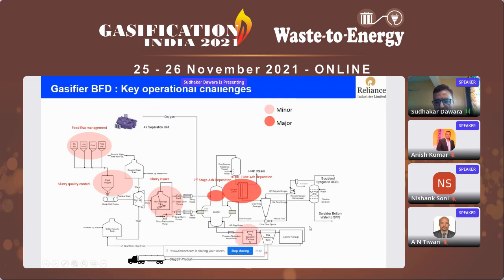Now, of course, we had many issues in the char filter. We have overcome that. We redesigned the metallurgy and the filtration rating, and a lot of studies were done, and now we have come out of that. And I'm happy to inform that our char filter run length has gone as high as 300 days on slurry operations. We had little issues in the carbon recovery package, because initially our carbon conversion was not right. A lot of carbon was getting into that stream. We have sorted this out based on gasification temperature and other optimization.